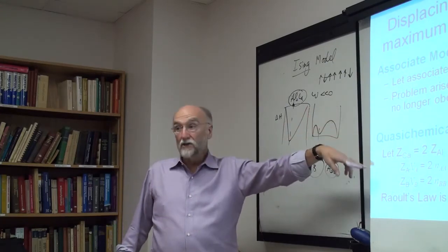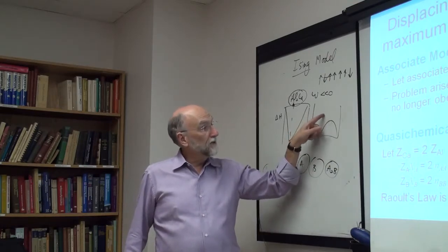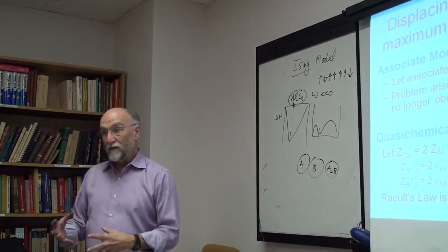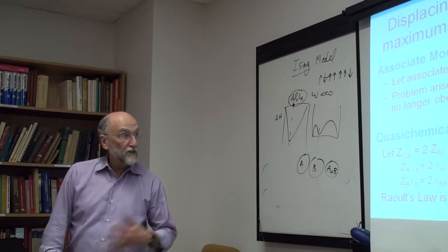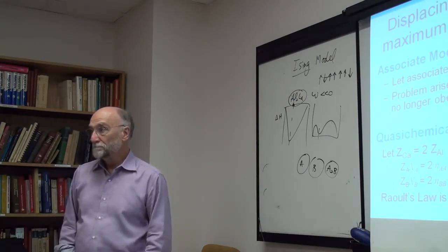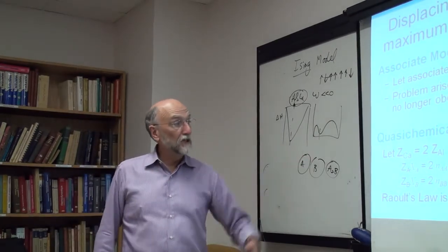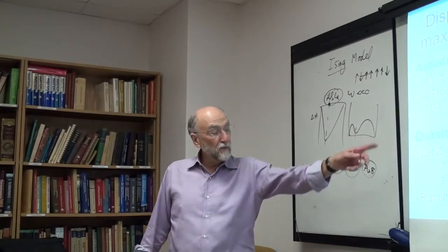The local coordination number around a calcium can be different from the local coordination number around aluminum because you don't have a rigid lattice. If you're dealing with a solid with a rigid lattice, you can't do this: you're replacing aluminums by calcium in a rigid lattice, and the calciums have to have the same coordination number as the aluminum they're replacing. But this is possible in a liquid.